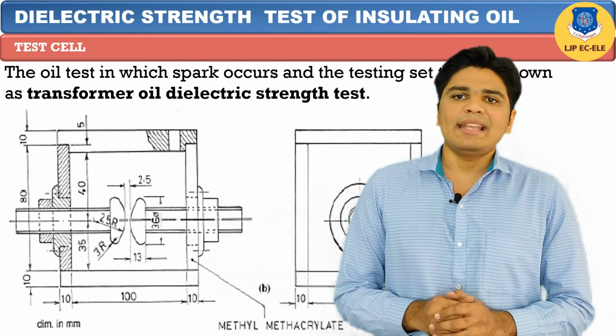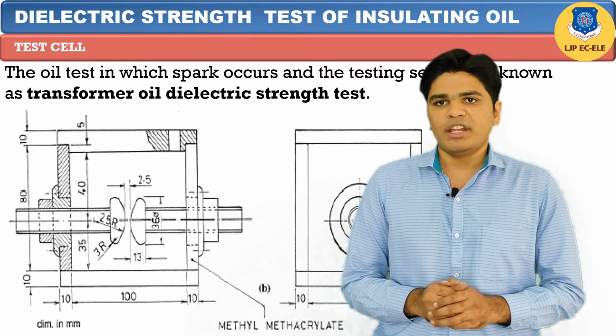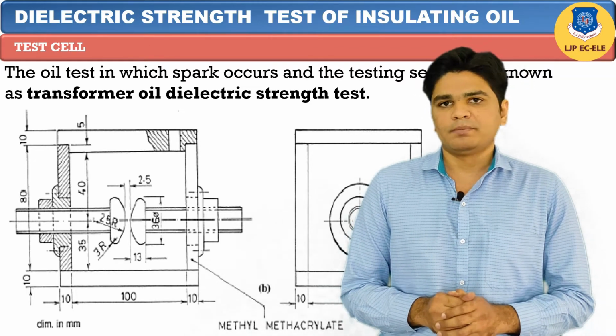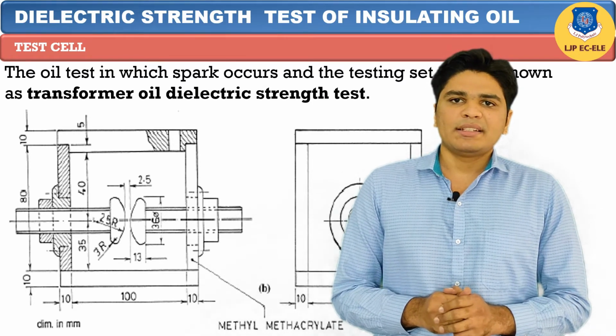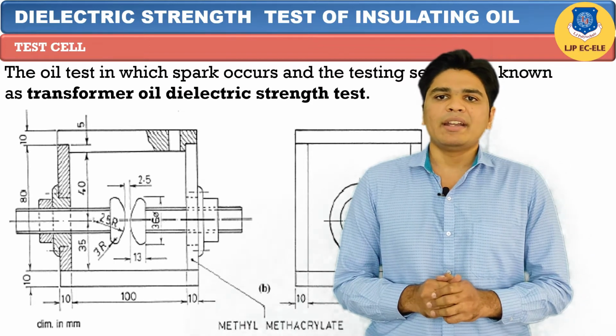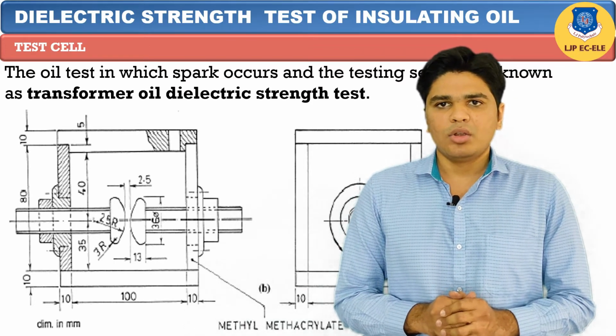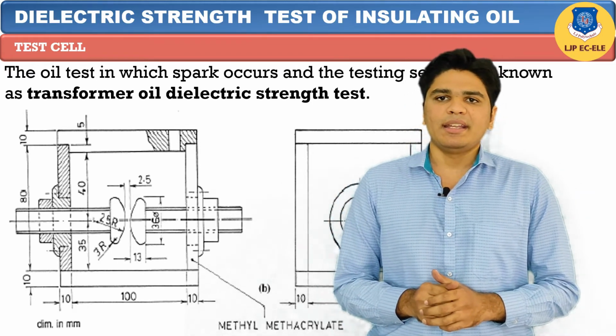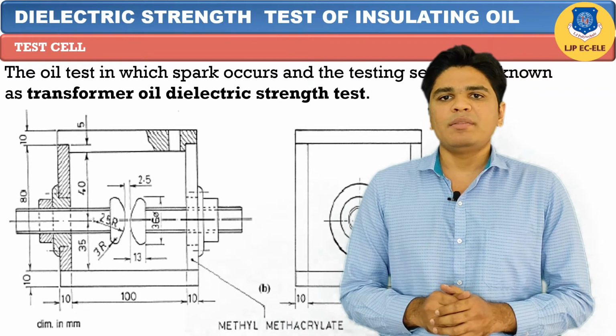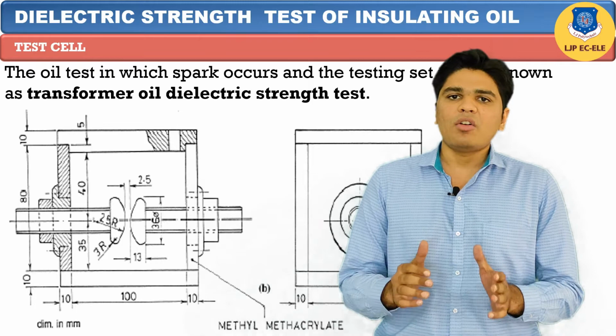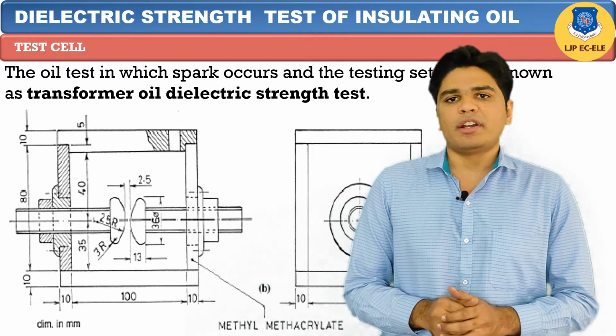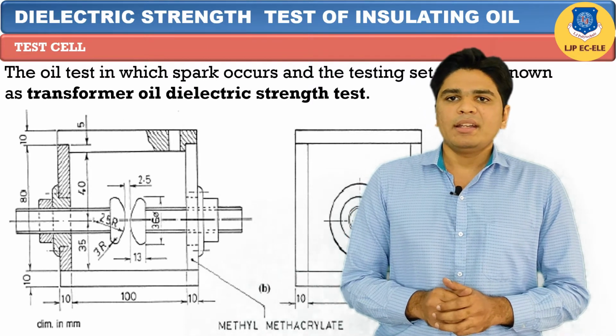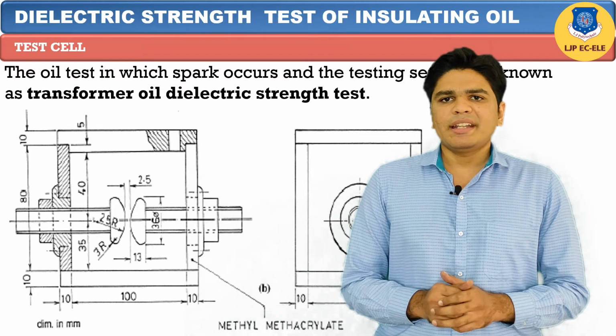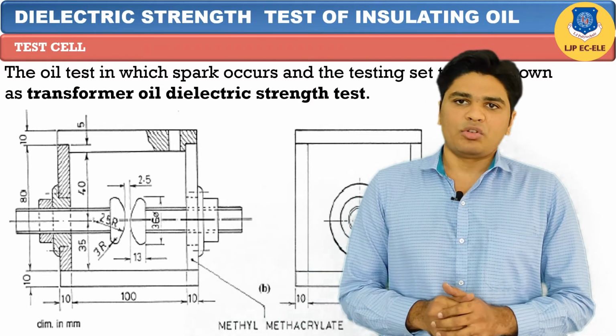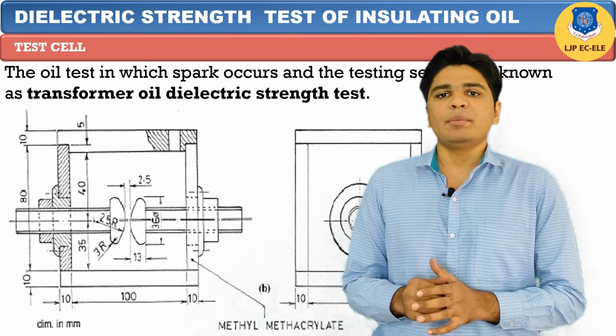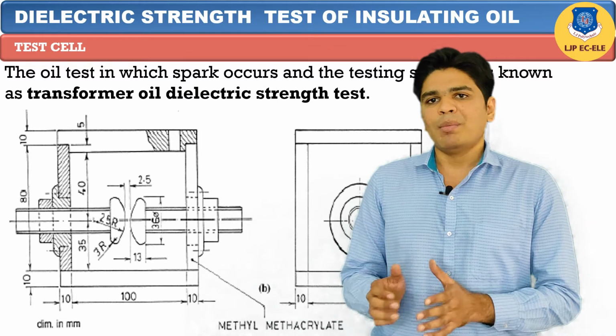A dielectric strength lower than 30 kV for a 4 mm gap of electrodes would indicate the presence of moisture in the oil. The recommended size of the glass test cell is 55 by 90 by 100 mm. The diameter of the spheres or test electrodes has been specified as 12.7 mm and the air gap between the spheres as 4 mm. The test sample should be drawn from the bottom of a drum, transformer or other apparatus. The oil in the test cell should be at least 40 mm above the electrodes, and it should be allowed to stand for 20 minutes before performing the test to let air bubbles escape.